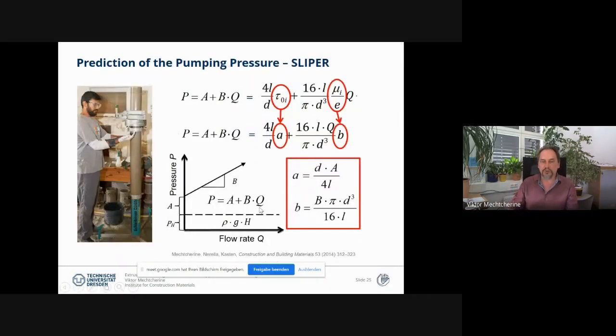So finally here, I want also to address the possibility to get pretty directly input for prediction formula by using not the sophisticated tribometer or viscometer, but rather this kind of a slide and pipe rheometer, which mimics the movement of concrete directly in the pipeline by actually moving here concrete in a small pipe and measuring here the pressure established on a sensor. So actually we can extrapolate this result to a real pipeline, and our experience is very positive with this approach. We have really very, very good prediction of the real conditions in the pipeline.